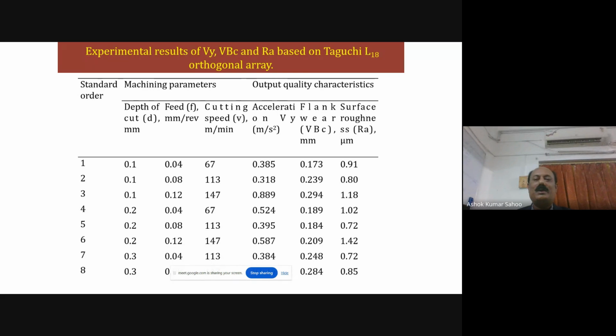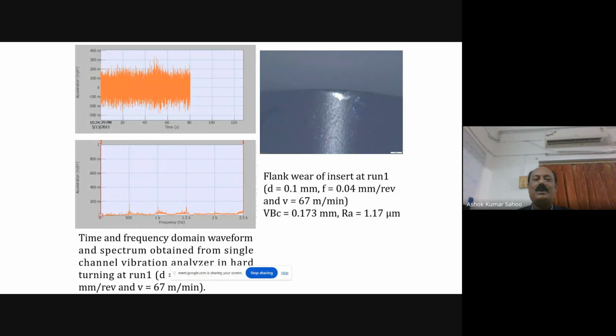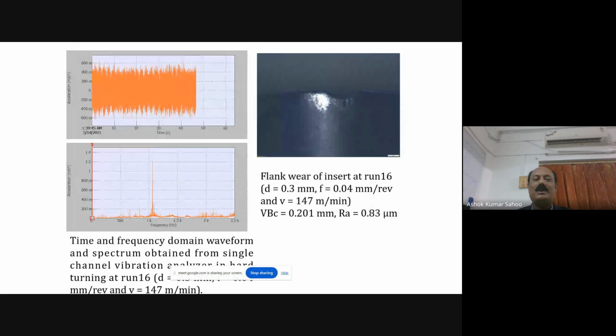We conducted experiments using a Taguchi L18 orthogonal array, considering three important process parameters: cutting speed, feed, and depth of cut. The output responses are the amplitude of vibrations, flank wear, and surface roughness. This is the acceleration amplitude of vibration in both time and frequency waveform observed during machining at run number 1. At that time, the cutting tool wear is very minimal because it is operated at a lower cutting speed and feed rate, so the waveform amplitude of vibration is quite low. Similarly, it increases as the wear progresses. When it is operated at a higher cutting speed of 147 meter per minute, the amplitudes of vibration in both the time and frequency domains are higher, as is clearly observed in both waveforms.